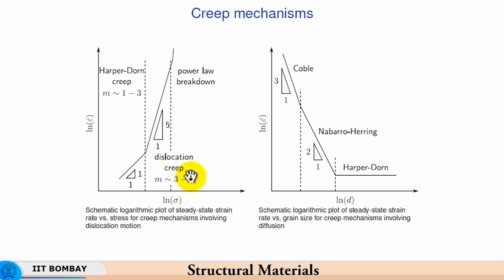Why? Because now the dislocations can climb, they can overcome the obstacles. So, for a relatively low stress, or a small change in stress, the strain rate can go up quite significantly. So, even if you have dislocation creep, by virtue of dislocation climb being facilitated, you get much higher strain rates.